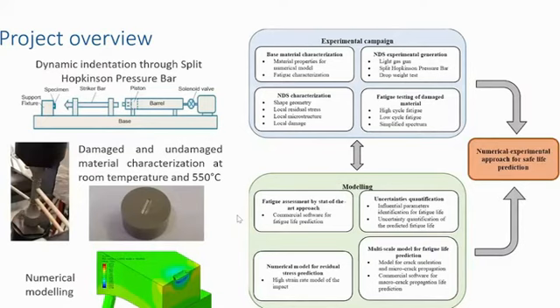The approach we use for the project is divided into 2 main activities: an experimental campaign and a modeling activity. In the experimental campaign, we are going to characterize the material, Inconel 718, in its elastoplastic properties, fracture properties, and fatigue properties. Then we're going to develop the damage with dynamic indentation using a split Hopkinson pressure bar. The damage is developed in fatigue specimens, and it is going to be characterized from microscopy images, and also the residual stresses beneath the damage are going to be characterized. Then the specimens are going to be tested to retrieve the low cycle and high cycle fatigue properties at room temperature and 550 degrees, where 550 degrees is the operative temperature of the turbine blade.